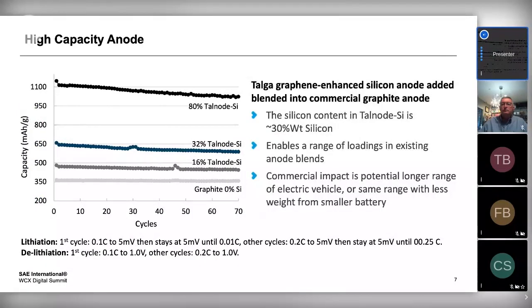And just to sort of summarize then, what's the end result? Well, today, down the bottom of this graph, you have graphite with no silicon at about 350, 360 milliamp hours per gram capacity. And as you sequentially add more and more silicon, you can see on this graph that by the time you add 80% of our combined graphene silicon product, you have nearly 3 times the capacity,